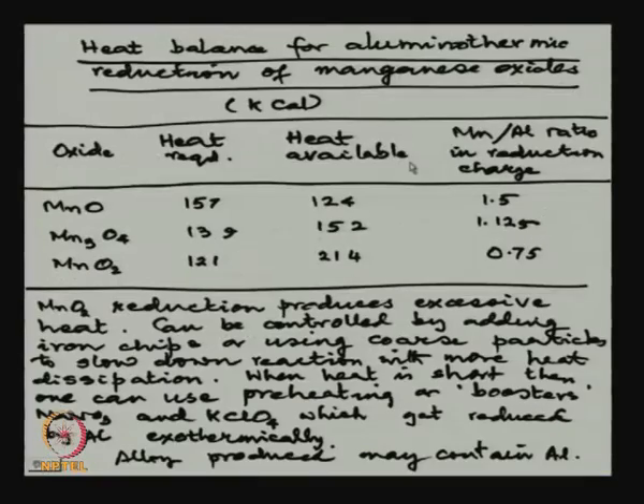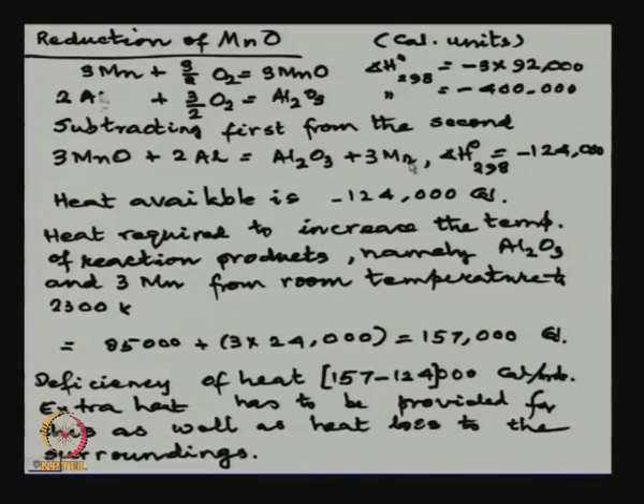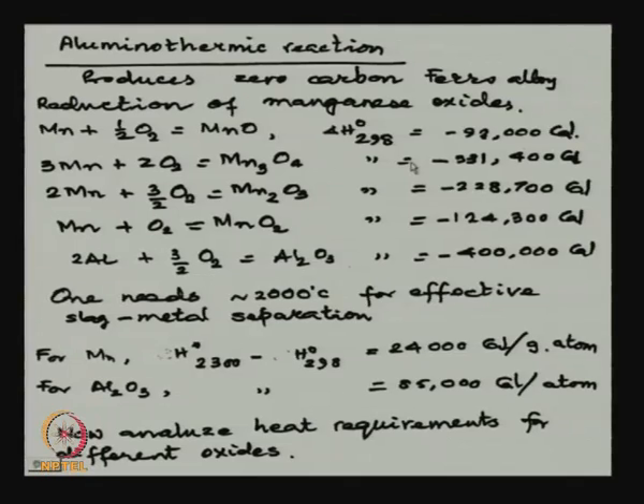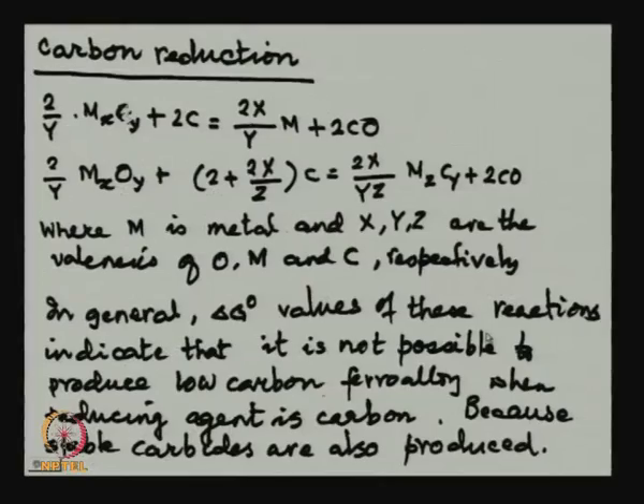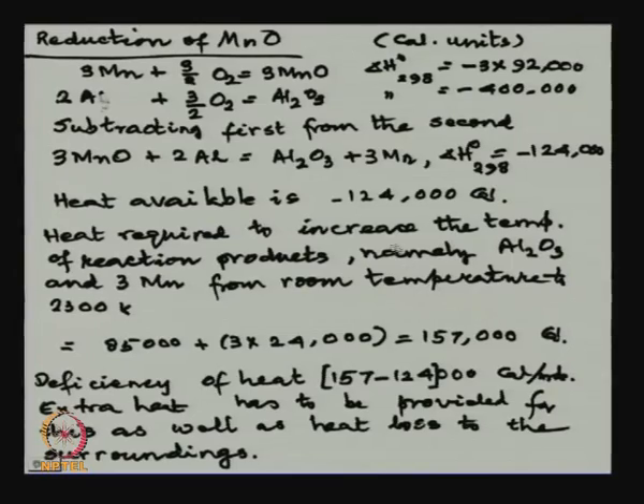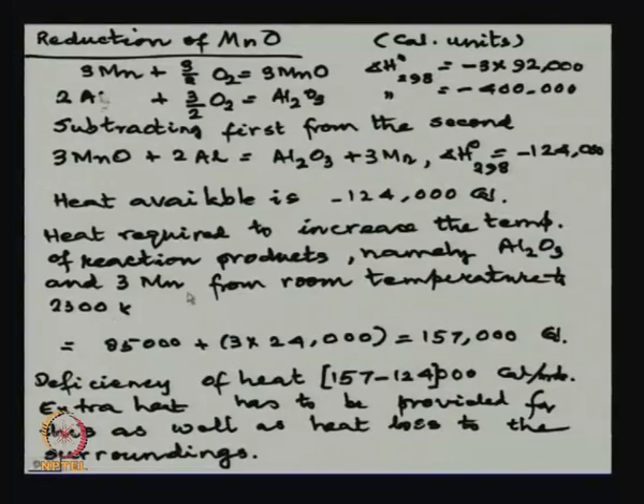Whereas, how much heat would we actually need, we will find that out. Now, the heat available is this much. Now, heat required to increase the temperature of reaction products, namely Al2O3 and Mn, from room temperature to 2300 K, because that is the final temperature we are aiming at for clear slag metal separation, we can find out from here. This into this is the amount of heat that we really need.